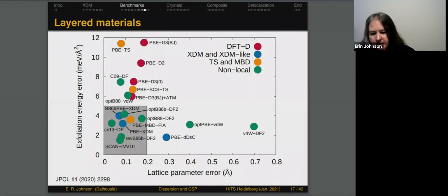It's only with some of the non-local methods, our XDM methods, and the fractionally ionic variant of many-body dispersion that we obtain good performance for both of these quantities, the exfoliation energy and lattice parameters. So again, this emphasizes the need for a density-dependent dispersion correction, one that is able to respond to changes in the chemical environment of an atom. In the physics literature, this is typically referred to as electronic many-body effects that would be included in a many-body dispersion method. All